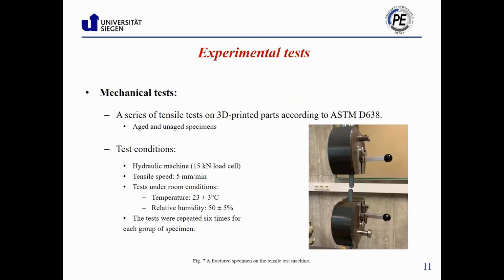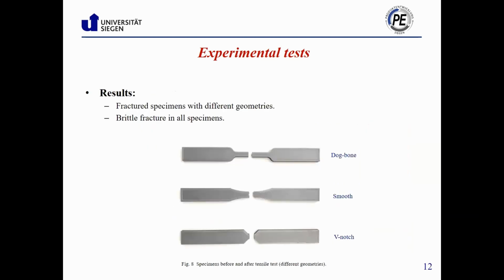A series of tensile tests on the aged and unaged specimens were performed under laboratory condition, and repeating the test on each group of the specimens and obtaining similar results confirm repeatability of the test. Here you can see the fractured specimens with different geometry, and in this experimental test, brittle fracture was observed in all specimens: dog bone, smooth, and V-notch.